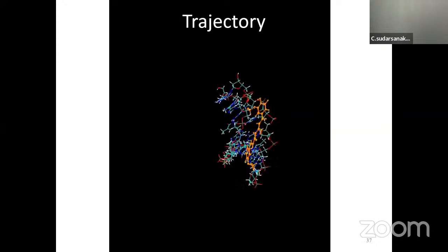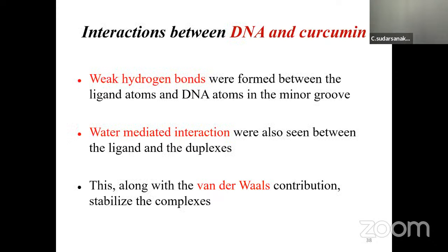So this is a small stretch of DNA, a small stretch of the trajectory. So you can have reasonably good computational methods available to extract the details from that. When you analyze it, what you find is weak hydrogen bonds formed between the ligand and the DNA atoms in the minor groove. And you find water-mediated interactions and van der Waals interaction. These are the major contributions to keep the drug molecule in the minor groove.